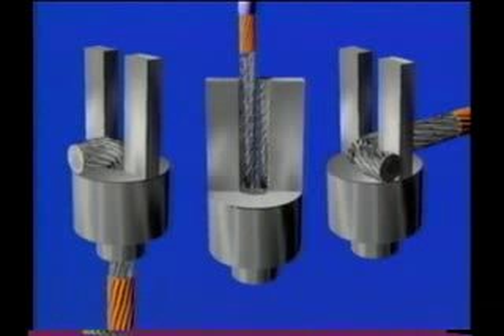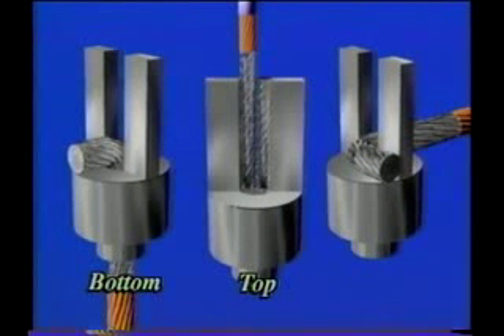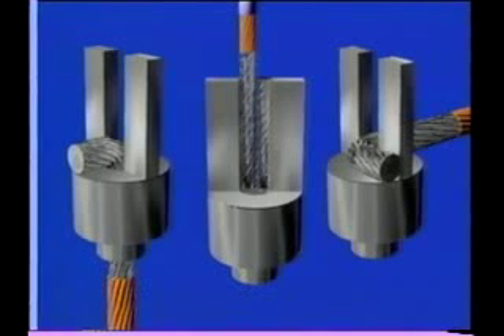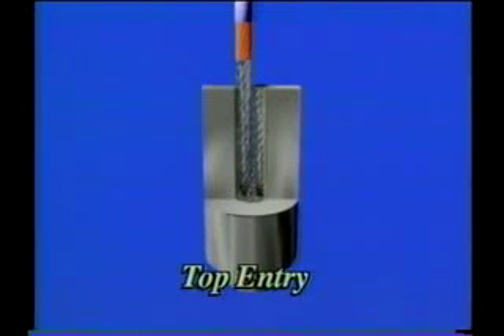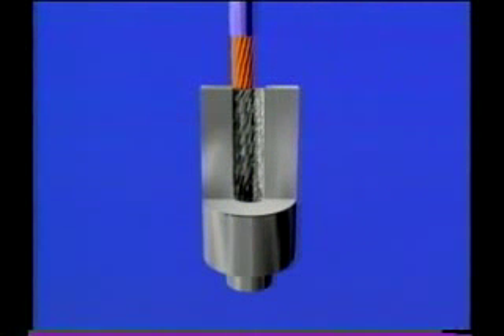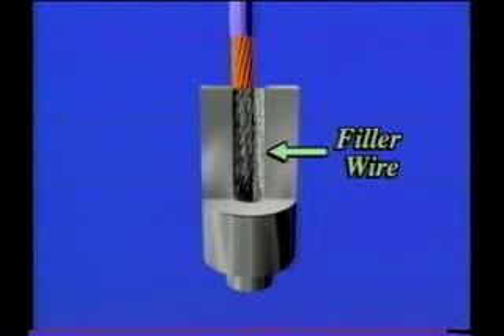In addition to side entry, wires may also enter from the top or bottom. For top entry of bifurcated terminals, the tinned wire is bent to double thickness. The bent wire is inserted between the forks and then soldered. If the wire is too large for double thickness, a filler wire is cut to length and added to fill the space.